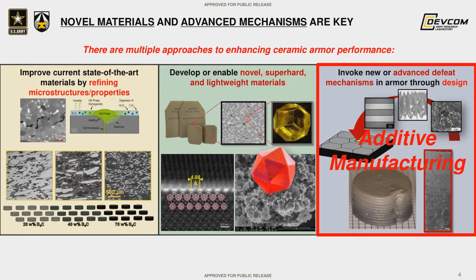Yeah, so as I was saying, one way we can do this is by improving the state-of-the-art materials that we have, namely boron carbide and silicon carbide, by doing things like refining the microstructure, controlling the grain boundary phases, and sintering mechanisms to maximize density, minimize grain growth, and enhance advantageous failure mechanisms such as transgranular or intergranular fracture inside the material to make it stronger.